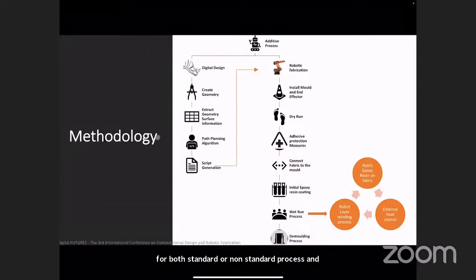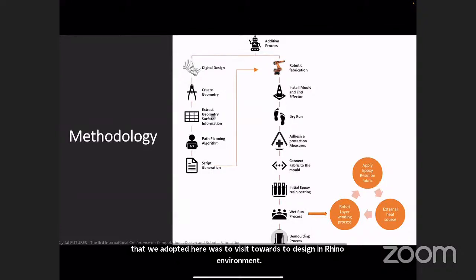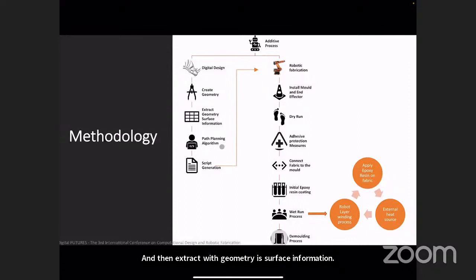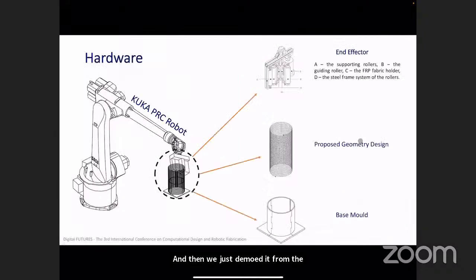The methodology that we adopted here was to design in the Rhino environment, then extract the geometry surface information, use the path planning method with the KUKA robot, and then start the fabrication process. In the fabrication process, we use epoxy resin as an adhesive, and for quicker curing we use a heat gun, and then we demold it from the fabrication side. The KUKA robot involved here is shown here. The first part is the end effector.